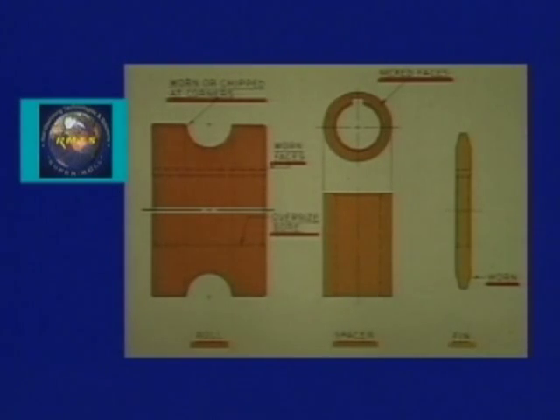Worn or chipped corners, of course, we're looking at the radiuses now. They can be inspected, and you can inspect them a lot of ways. We normally make gauges for you with your tube mills if you like, and the gauge would sit in the tube mill, and you would see how the radius looks to find out how bad or how good that is. You can check the root diameter, which is the dimension between here and here, but normally it will not stop you from running. This problem will hurt you, this problem will hurt you, and also this problem here, the radius being blown at the last sizing pass, will hurt you.